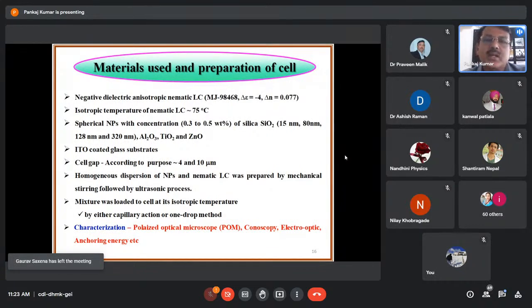Not only silica, there are different materials: alumina, titanium oxide, zinc oxide, silica, etc. And different sizes of nanoparticles have been used. You can see here 15 nanometer, 80 nanometer, 128 nanometer, and 320 nanometers. As we have been doing these experiments for many years, the sizes 15, 80, 128 and 320 are the most appropriate. After that, we have used 540 nanometer, 700 nanometer, 800 nanometer, 1000 nanometer, but these scale nanoparticles are not up to the mark when we talk about display devices.